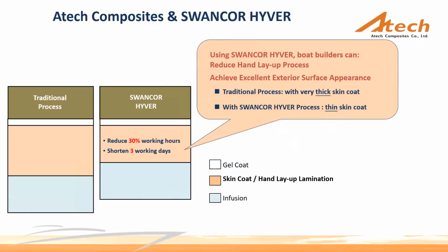But some people may say using unsaturated polyester can build a boat which also has a nice surface. Honestly, they are right, because we did it with the same idea before HYVER application. In order to block the fiber or the grooving pattern from being printed on the surface, the builders always lay up a skin coat after spraying the gel coat. Generally, the skin coat is made by hand lamination and it is a resin-rich layer and it is always thick. The builder would build a thick skin coat to block the print-through phenomenon.